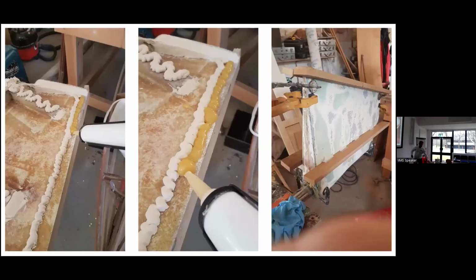This is a great point. I mentioned the G-Flex product. This area here is a brilliant use of G-Flex because it bonds incredibly well to metal, but it also has a degree of ductility to it. So where you've got metal entering that moulding, the last thing you want is something rigid. I would imagine that has been the source of water ingress on this rudder, because in the boatyard they would have only had polyester bonding paste, or even worse, resin mixed with French chalk or something, which is very, very brittle and doesn't bond well to the stainless steel.